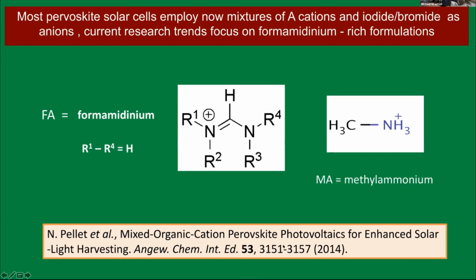So we take credit, with Professor Meyer again, for having discovered that the formamidinium lead iodide is not stable at room temperature. It forms a delta phase that is yellow and is useless for photovoltaics. So you have to go over 160 degrees to stabilize the alpha form, the desired black form. So that's a problem, and formamidinium is preferred over methyl ammonium because it's more stable, it doesn't decompose. And it also has, the lead iodide salt has better optoelectronic properties.